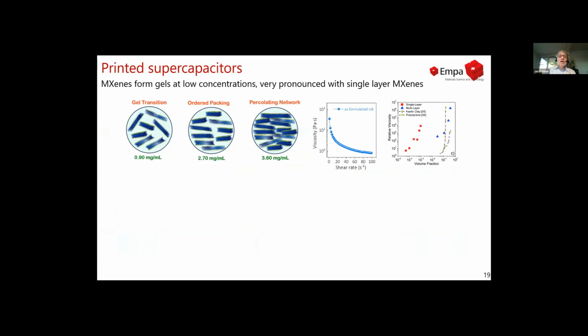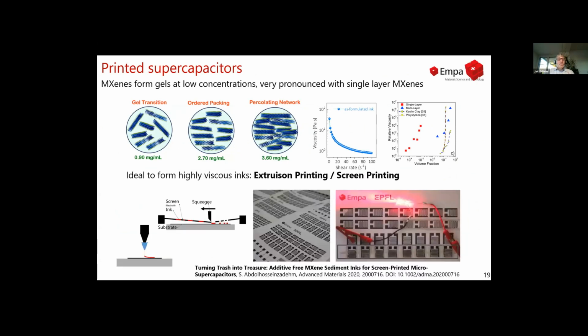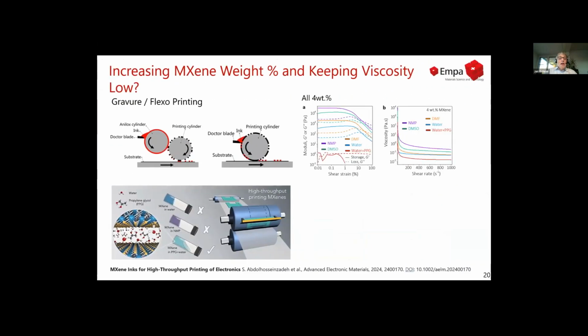Very strong interactions between these MXenes actually lead to very, very high viscosity inks already at low concentration. So that's very suitable for screen printing, extrusion printing. So here are examples of how we print supercapacitors, also similar to the previous speaker. We also adapt these inks for gravure printing.